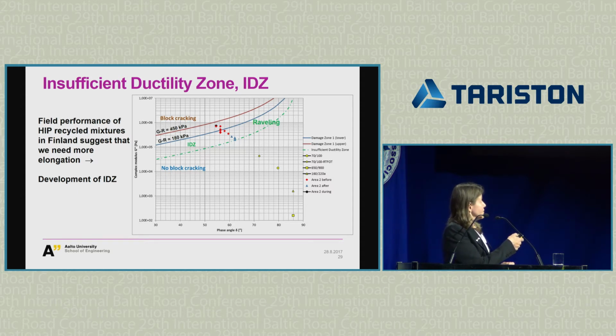So here are the samples we took from before recycling, and here is the final product that was the outcome after rejuvenating the mixes with softer bitumen. So we were in this damage zone, and then we came out of it. But then we did some visual inspection and monitoring of the road for 2-3 years, and started to realize that, okay, we came out of this damage zone, but there was still damage, there was raveling. And that came the idea that maybe in Finland, because the study was done in the United States, there are different mixes, WesTrack mixes, they are on the West Coast and so forth. So maybe our mixes are different, and even though we would have exactly the same binder, we wouldn't have the same performance.